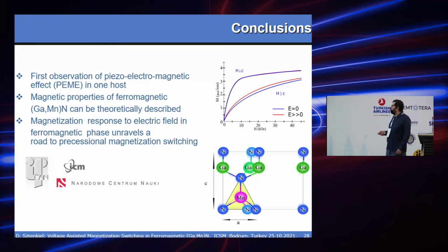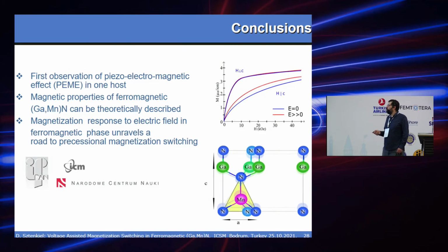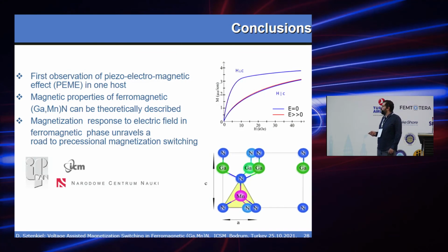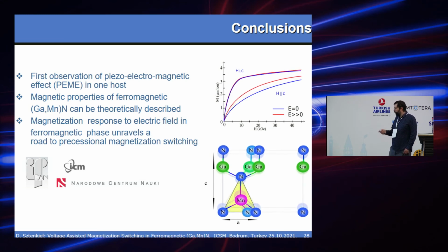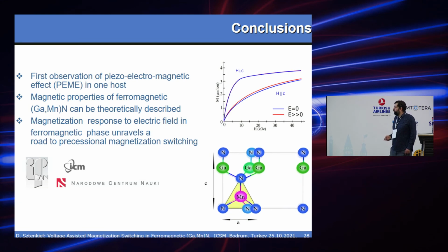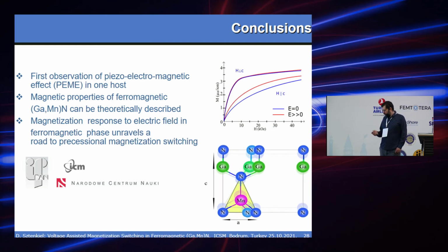And finally, conclusions. We observed the piezoelectromagnetic effect in the ferromagnetic state of our material. We showed that we can control the magnetic coercive field by AC electric field, and we can also induce the switching of the magnetization by electric field, and we can describe experimental data using an atomistic spin model and Landau-Lifshitz-Gilbert dynamics.